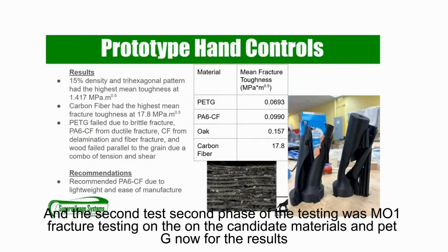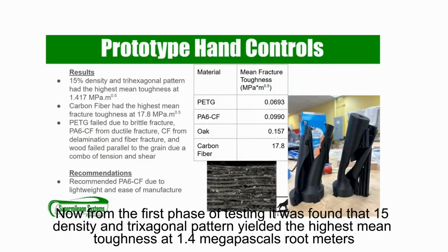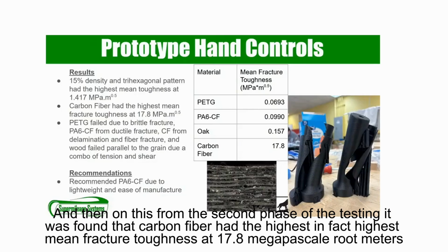Now for the results. From the first phase of testing, it was found that 15% density in a trihexagonal pattern yielded the highest mean toughness at 1.4 megapascals root meters. And then from the second phase of the testing, it was found that carbon fiber had the highest mean fracture toughness at 17.8 megapascal root meters.